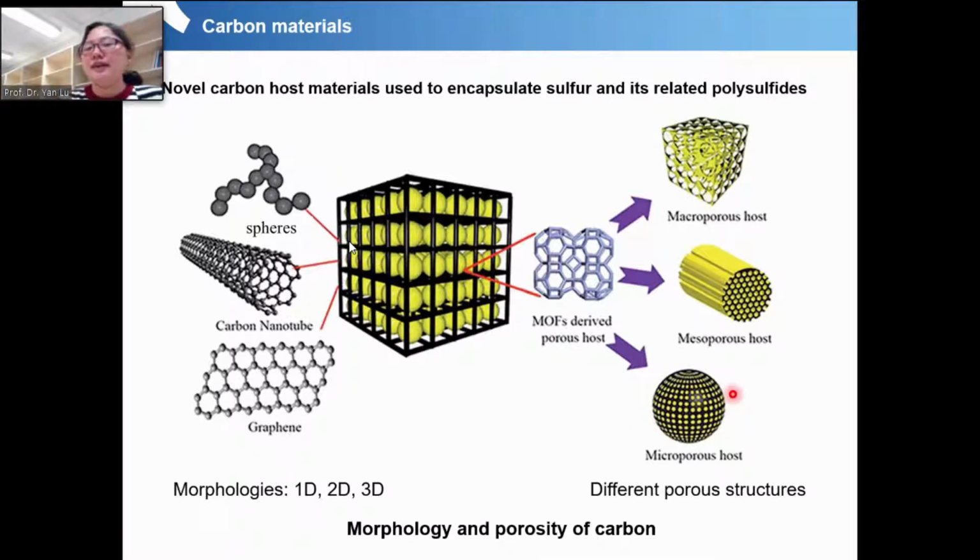And I just want to mention that for the sulfur host, the mesoporous system is more promising because when we think about sulfur, it always exists not as single atoms but as molecules. You always have S8. So if your pore is extremely small, this 8-atom sulfur molecule cannot go into such small pores. That's why microporous carbon is actually not an optimized cathode system for sulfur.